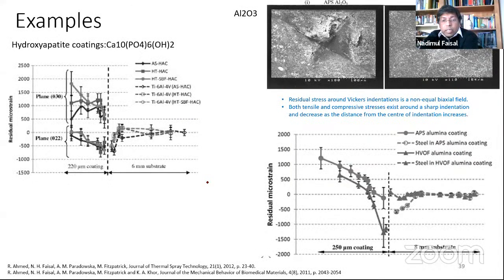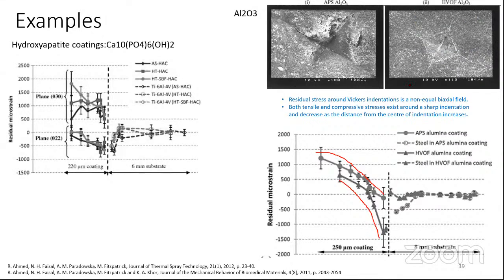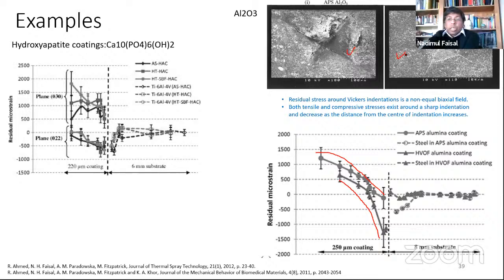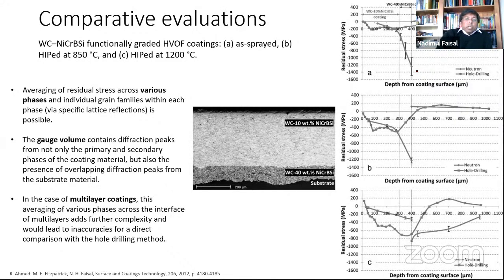So these are some of the examples we have done on hydroxyapatite biomaterial, as well as alumina coating. And you can see here for one coating type, the strain is largely tensile. For another type, you can see you've got a lot of compressive strain. And we did indentation on those two samples. You can see the surface fracture is a bit different. So the high tensile residual stress here would have impacted the failure of this plasma sprayed alumina coating. However, for HVOF, the pattern is comparable to some of the standard fracture mechanics in indentation. There is very little work available where comparative analysis has been done.